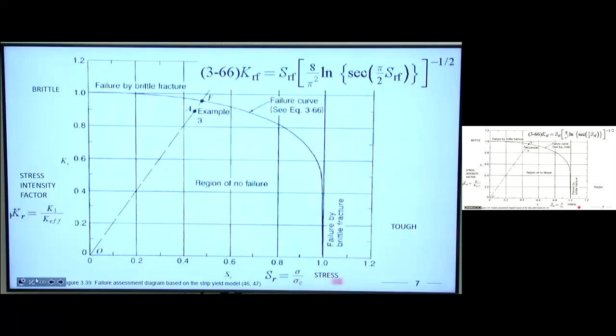And so we get up to that threshold by looking at the stress that's in a part. And so if we look at the stress that we have on our component and normalize it by that collapse stress, sigma C, that's the x-axis here. So if we are at the critical stress, this collapse stress, then this equals 1. And we would expect a failure, and it would have a fracture over the whole region, and it would be more of like the whole region failing. And so that's the x-axis here. And so it allows us to go from that point, that mode of failure, between that and another one, which would be a brittle crack propagation failure.